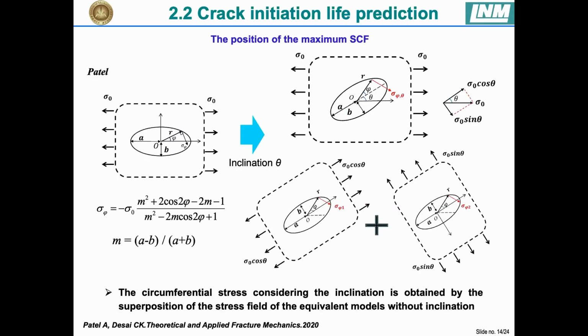And then for the position of the maximum stress concentration factor, Patel proposed a model of the circumferential stress along the pore edge in polar coordinates. But in this model, the inclination is not considered. When the inclination is taken into account, the applied stress can be decomposed along the inclination into two equivalent models, and the circumferential stress considering the inclination can be obtained by the superposition of the stress fields of the equivalent models without inclination.